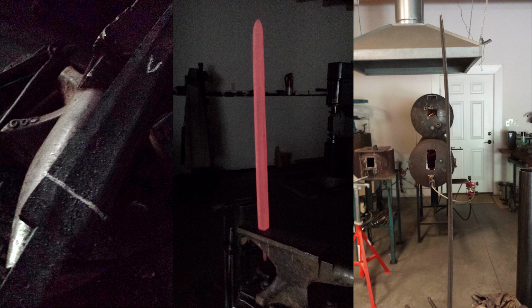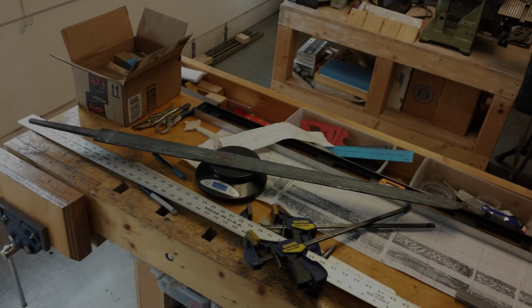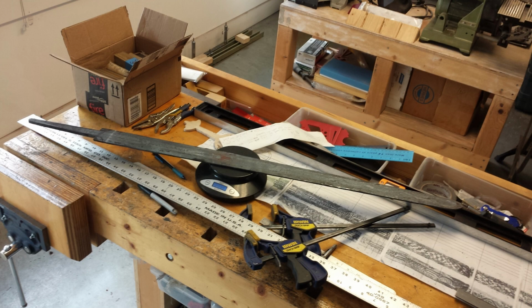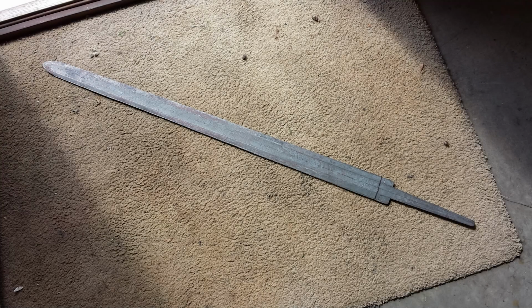Here you can see that I had forged the bevels and the fuller, and I was starting the heat treat process. Unfortunately, the blade ended up with a warp towards the point, which I was able to straighten at first. This was after heat treat, still way too heavy, but there is quite a bit of material left to remove. Another view, I have inscribed the lines to mark the bevels for the grinder.